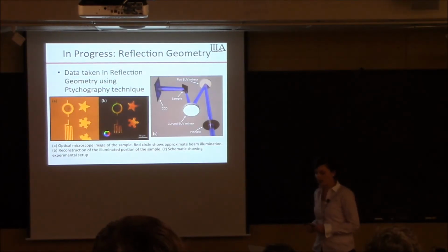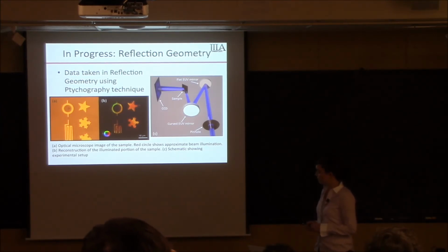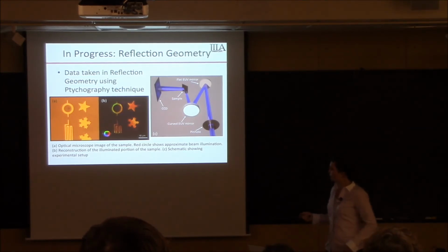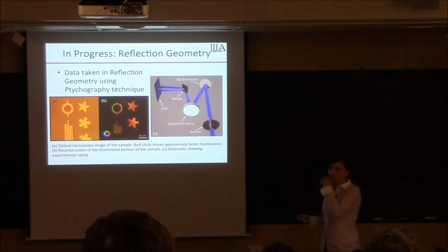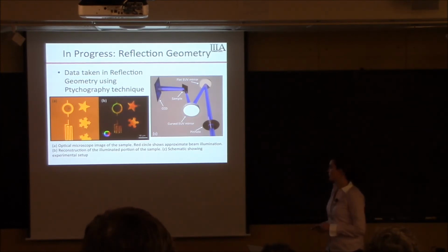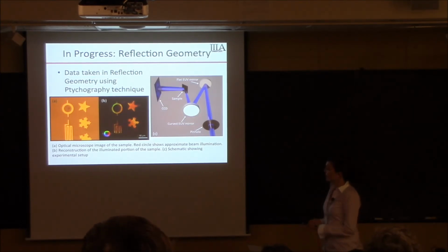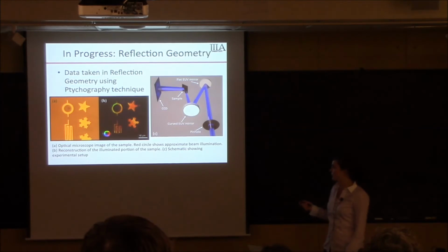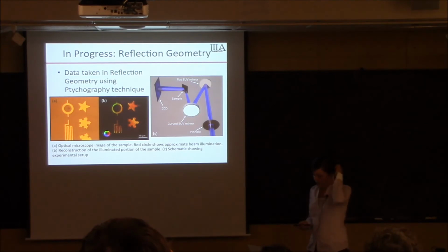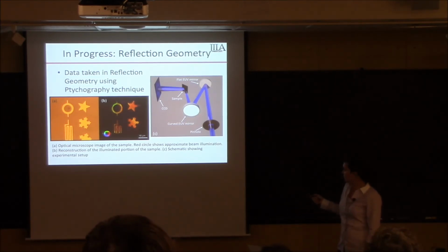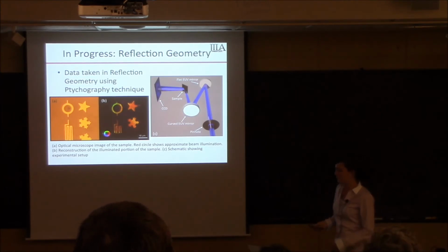We've just started taking data and doing reconstructions with EUV in reflection mode. So here's some pretty new results from the past couple weeks. This shows an optical microscope image of the sample, which is 30 nanometers of titanium patterned on silicon wafer. And this is showing the reconstruction of the complex amplitude, where the intensity corresponds to the amplitude and the color corresponds to the phase. And here's just a schematic of the setup. It's pretty simple, actually. It passes through a pinhole, reflects off of mirrors, hits the sample, and then is collected.